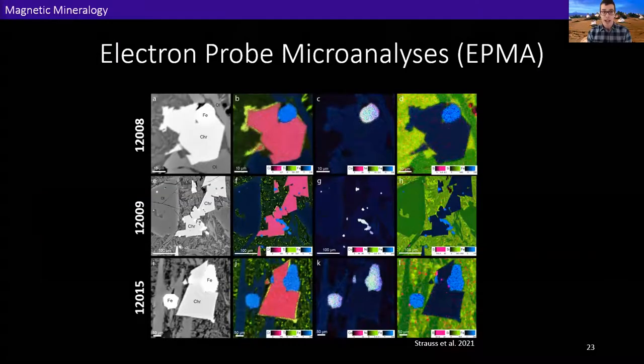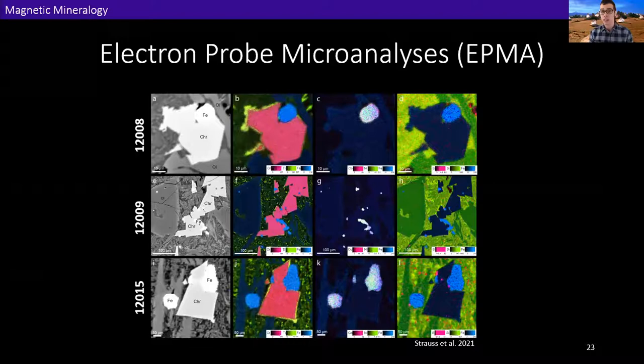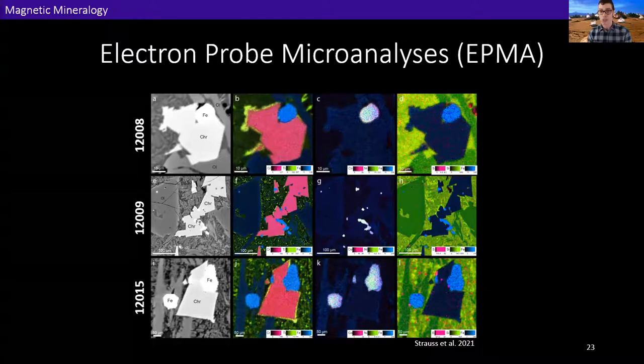So at Rutgers, we had access to an electron microprobe. What you're looking at here in the second through fourth columns are qualitative elemental X-ray maps, which we collected in addition to obtaining quantitative points from individual grains. You can basically think of each pixel in each image as representing a single data point. So if you look at the third column, which has this kind of navy blue background, we're showing iron in blue and nickel in green. And from that, we can say we were definitely seeing some actual iron nickel grains, which is pretty cool.